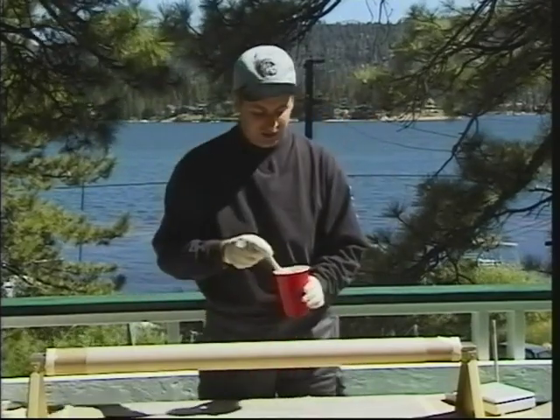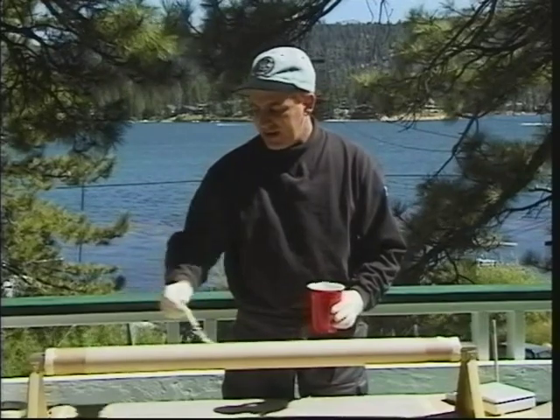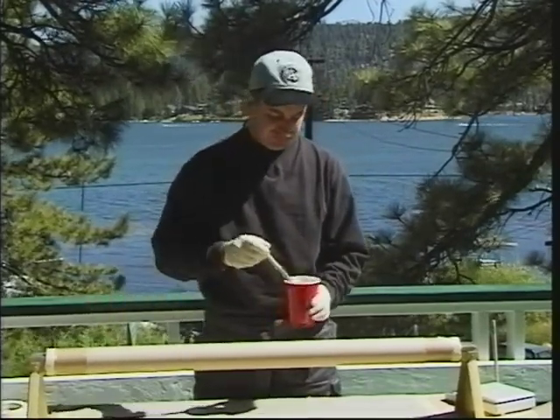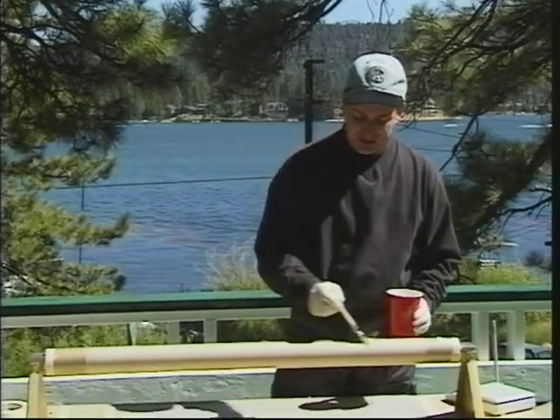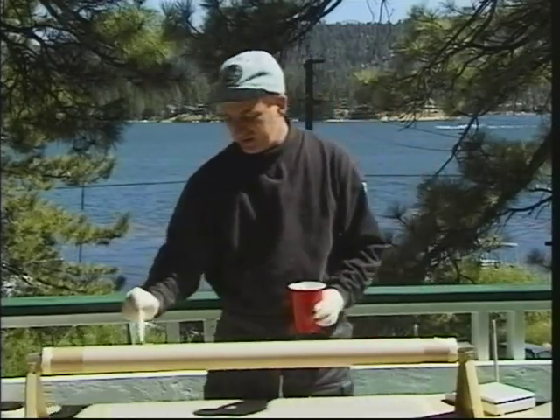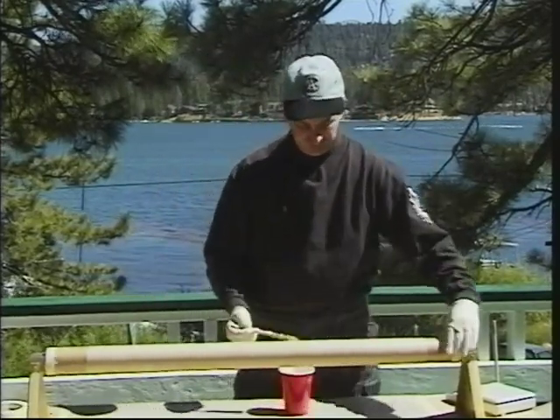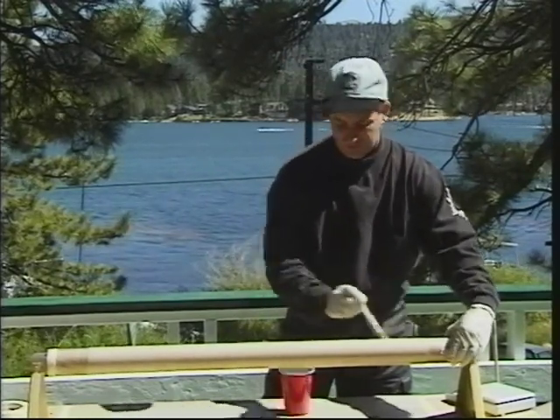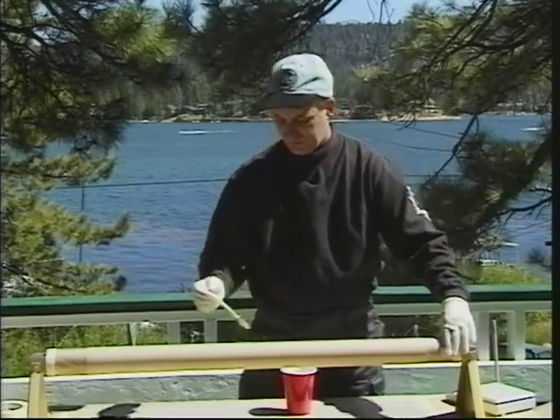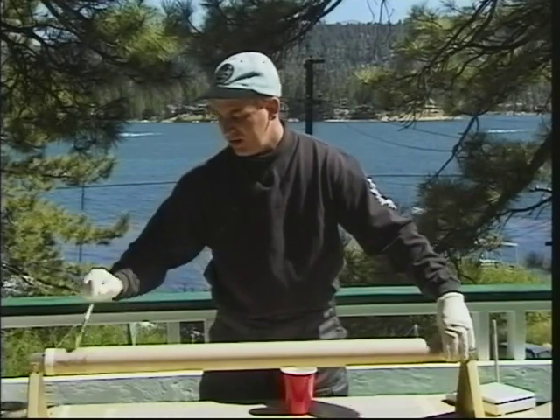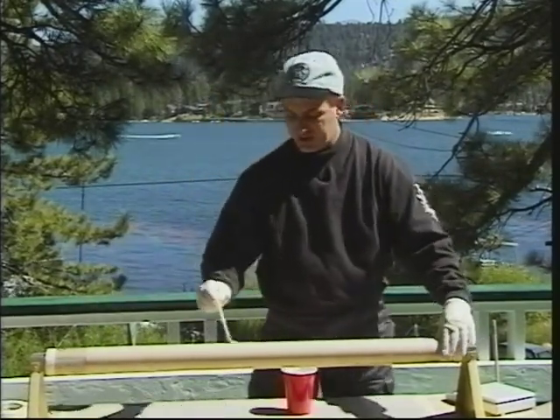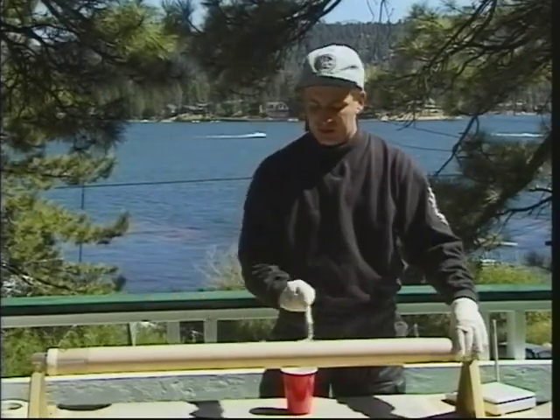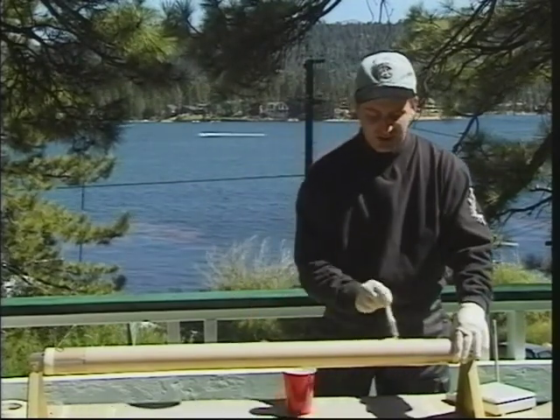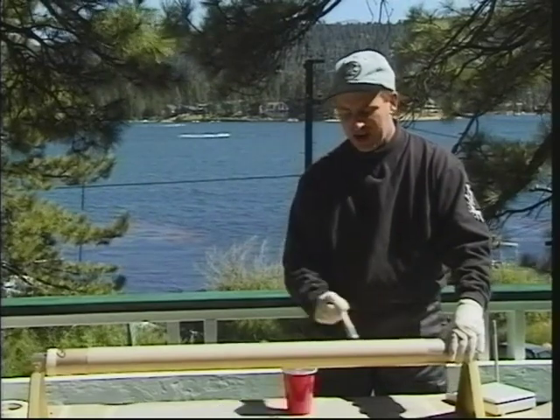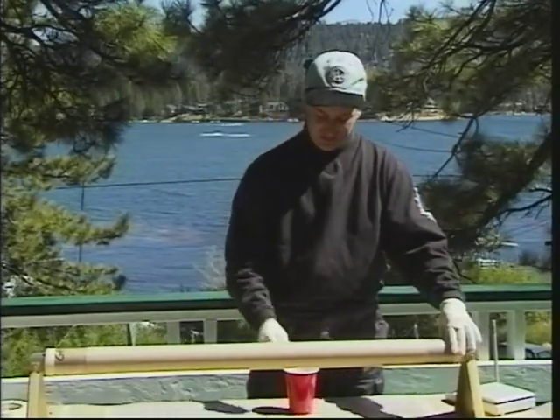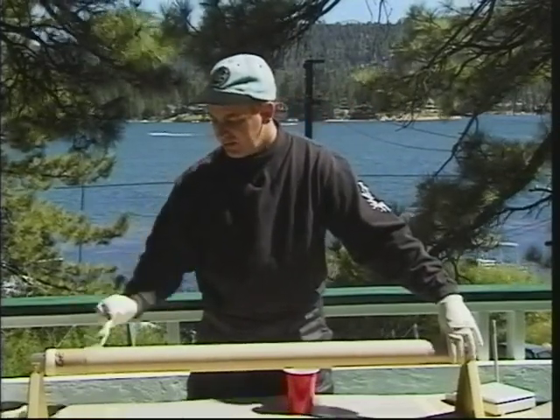except I'm going to be using a little more epoxy. I'm going to lay the epoxy on the whole tube this time. I'm not laying it on so it drips. I'm just giving a good gloss to the tube again so I get good adhesion to the tube. But we are going to be using more epoxy during the lamination process itself, and that's all in the interest of getting that epoxy into the fiber matrix of the cloth. If the epoxy isn't in the fiber matrix of the cloth, you have nothing. If it's just plain epoxy on the surface, or if it's just plain cloth, you have no strength whatsoever. So it's got to be the combination of the two.